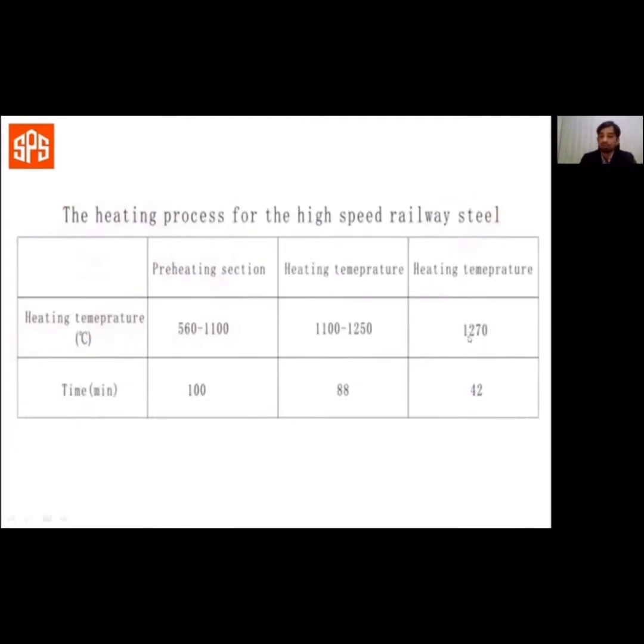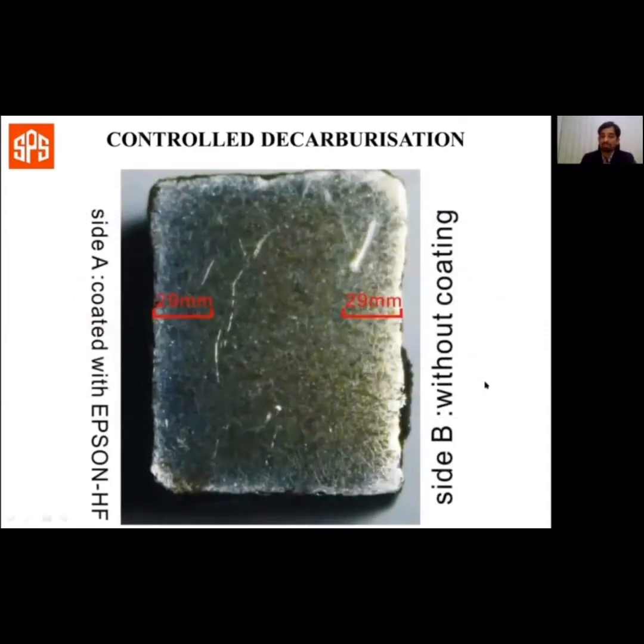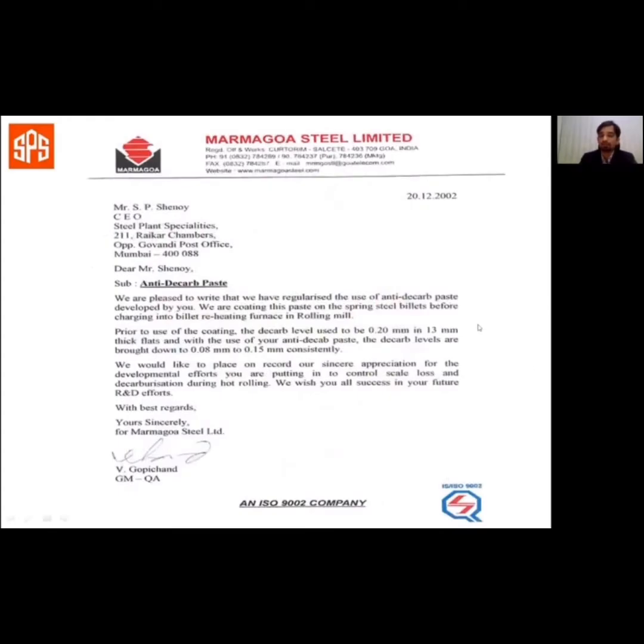Heated to 1270 degrees Celsius, soaked for 42 minutes. And the result, on the coated side, on the not coated side, you can see white decarb layer has penetrated deep. On the coated side, decarb is controlled well. A case study from Marmagao Steel Limited, decarb was 0.3 mm. The coating helped in bringing it down to 0.08 mm.